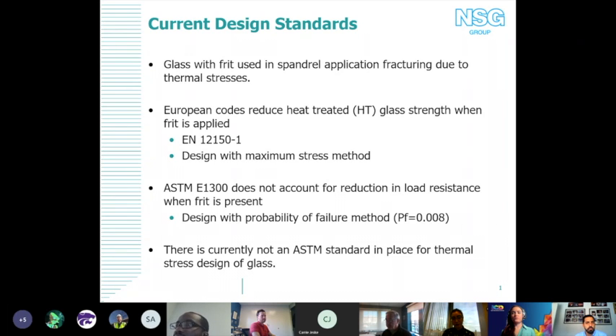One of the main differences between the two standards is that in the US, we design using a probability of failure method. So it's acknowledging that there are inherently critical flaws on the surface of the glass that can cause it to fail below whatever the maximum principal stress in the glass is at the time. Once the glass comes off the line and starts being processed and washed, you start gathering these little flaws called Griffith flaws on the surface of the glass, and they become locations for concentrated stress essentially. So in order to help prevent the potential to under design or over design, we design using a failure prediction model. Everything I present here, I'm going to focus on designing to the probability of failure of 8 in 1,000. And you'll see where I'm going from there.